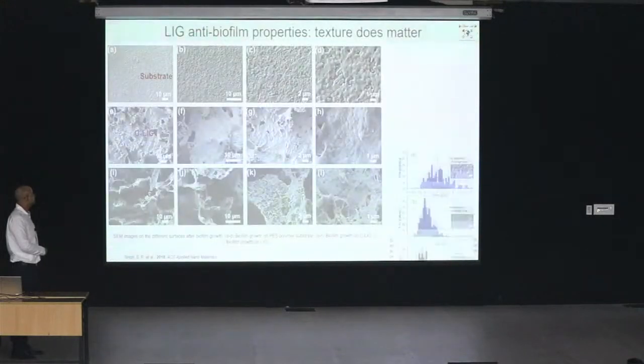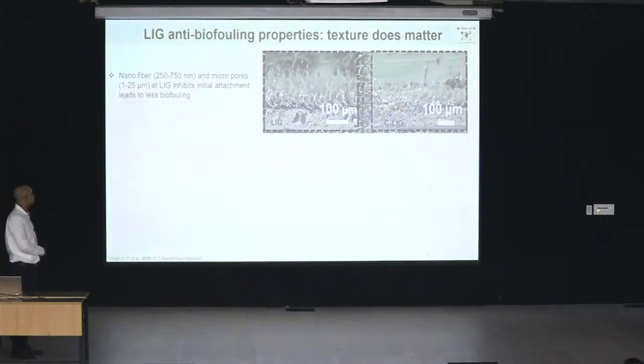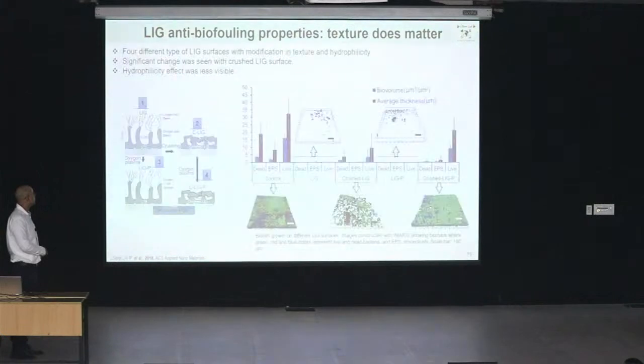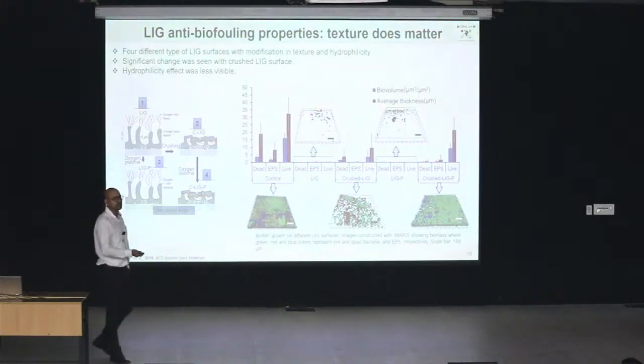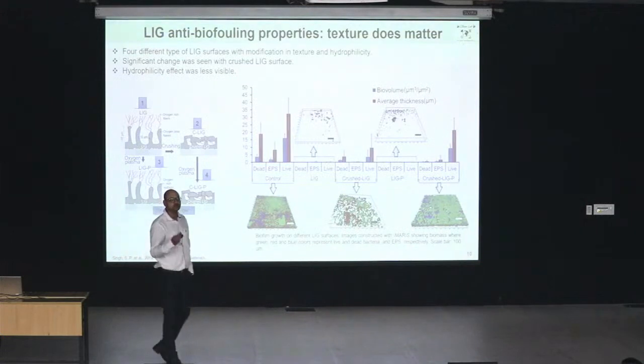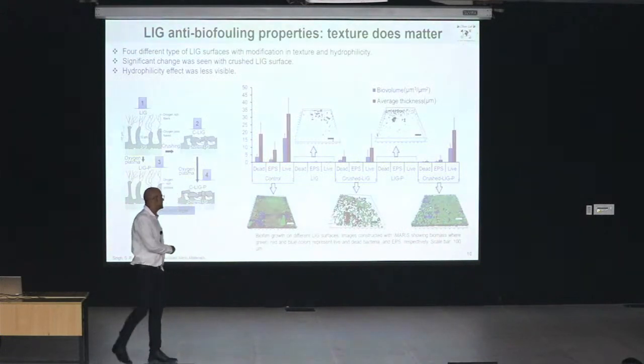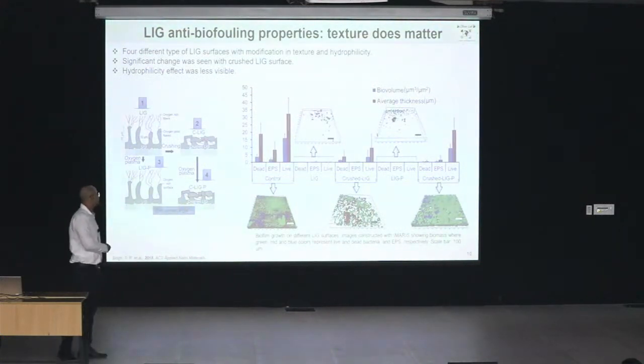which we have seen when we have crushed these surfaces. Then what we have seen, like a lot of biofouling growth, you can see when we have done the experiment with the crushed surfaces, we have seen growth on these surfaces, whereas on normal surfaces there was almost no growth. We have tried many other things to investigate whether some chemical release or something, but most of the time our conclusion was this is mostly texture based.